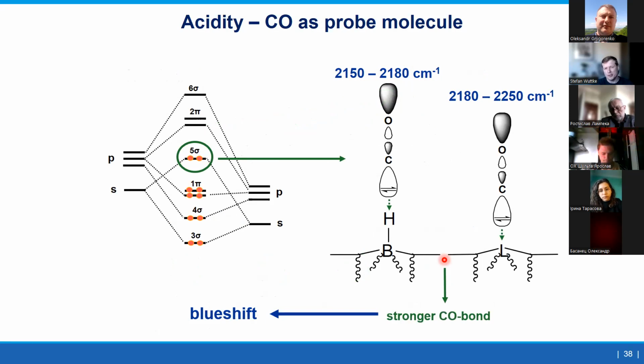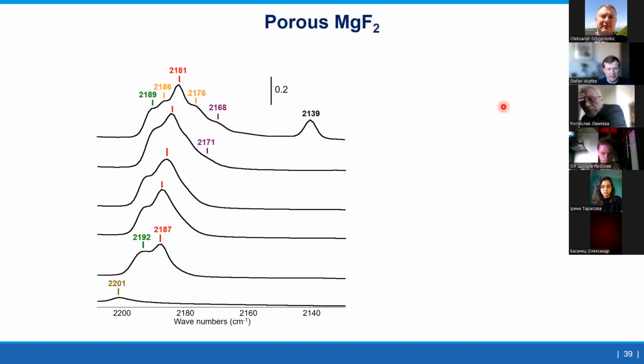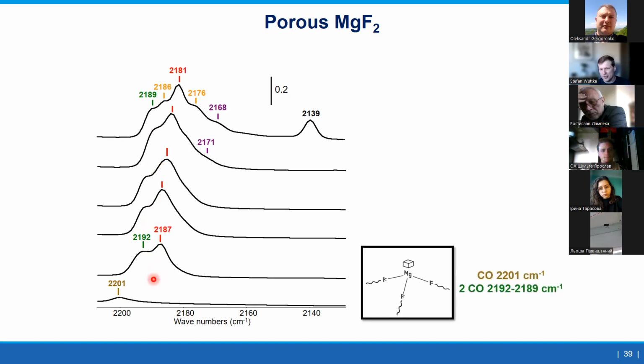And with this, we can monitor, and we know exactly that Bronsted acidity is much weaker than Lewis acidity. And these are the typical vibration modes, where CO is on Bronsted acidity, and here CO is on Lewis acidity. And what I did, so sorry when I say I, but this is really what I did. This was at the end of my PhD, magnesium fluoride. In my PhD, I did porous magnesium fluoride. And I tried to understand the Lewis acidity of the sample. So there was no Bronsted acidity. And what you always do is you put small amounts of CO. So you put a small amount on, then you see this, and then you put more and more CO, and then you see how the bands are shifting. And one important thing is that when you add the first CO, it always goes to the strongest Lewis acid site. It's clear.